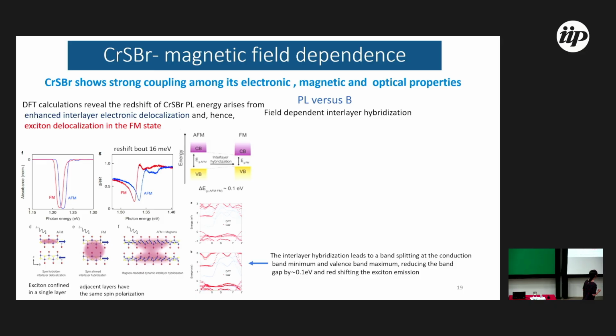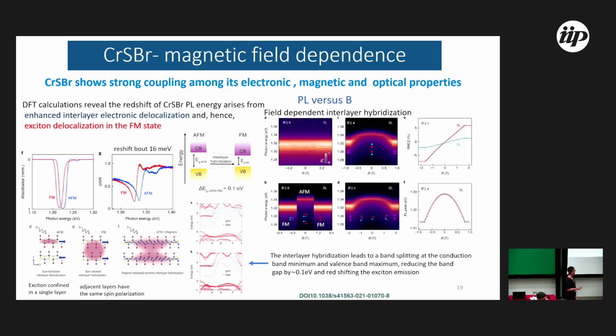Okay. So this pertains to the physics of the substrate still. For example, you can see clearly here the absorbance. You can see the energy is different for the two phases, and if you measure PL, you see the different energy for the ferromagnetic and antiferromagnetic phase. I forgot to mention that the monolayer is ferromagnetic, and the interlayer coupling makes the layers antiferromagnetic.